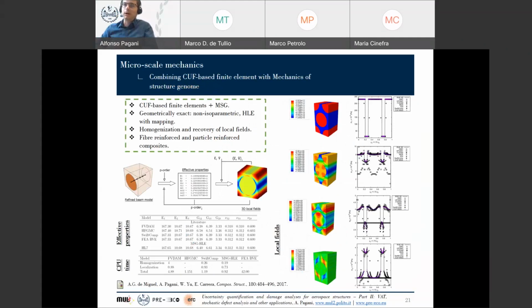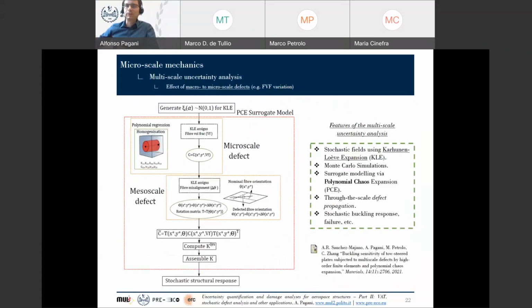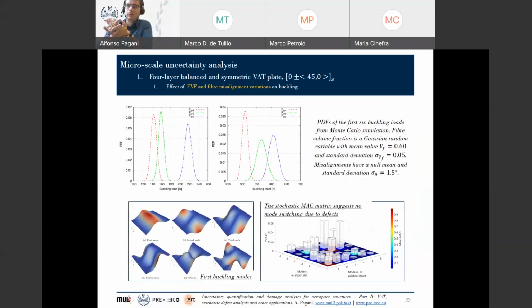In the next step, we are taking into account also some multi-scale defects. Professor Petrolo has shown the effects of voids. In this case, we are considering the effects of fiber volume fraction in the printing process. And for carrying out this multi-scale uncertainty analysis, we are combining our deterministic finite element models with surrogate modeling based on artificial intelligence and polynomial chaos expansion theories. And we are interested essentially in investigating the buckling performance of variable angle tow composites. So we are combining defects at the layer scale, such as fiber misalignment, and defects at the micro scale, such as fiber volume fraction.